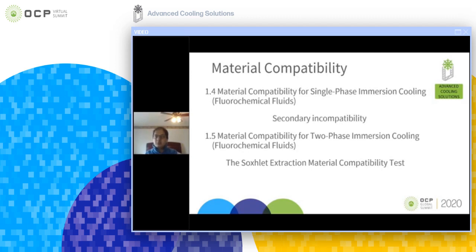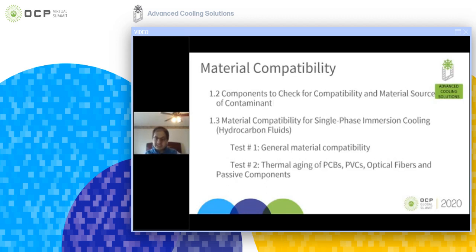Second is age testing, because the ASTM JEDEC standard is not applicable for immersion-cooled environments. It is only applicable for air-cooled environments because of the heat capacitance difference between the oil and the air. So accelerated thermal cycling will not be applicable here, but thermal aging can be a good experiment. So the second test is material compatibility using hydrocarbon oils for age testing of solders, QSFPs, and different components, active components, passive components, PVC cables, optical fibers, all of them.